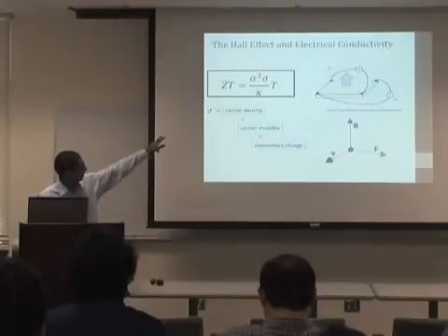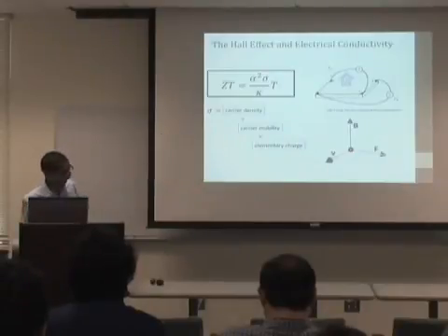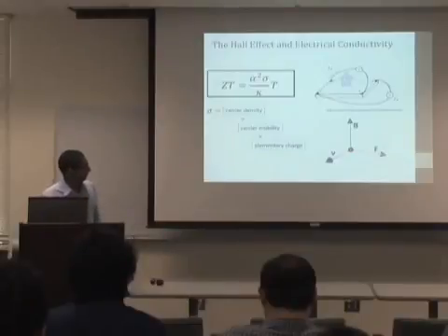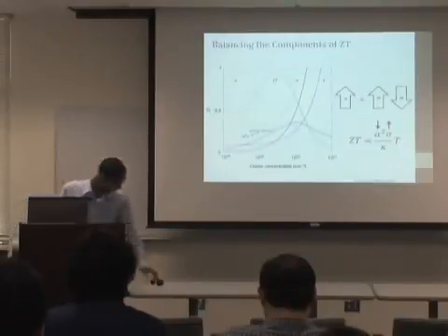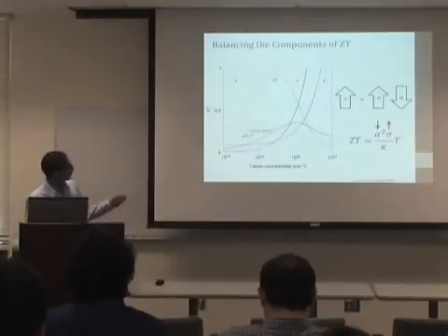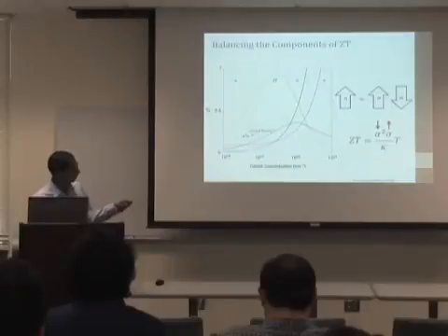And when we have those two values, and the elementary charge is a constant, we can gain information about the carrier mobility, which is also good information to have when you're looking at electronic transport. So going back to this trend, we're trying to find that peak, that optimal carrier concentration that can give us that peak in power factor.